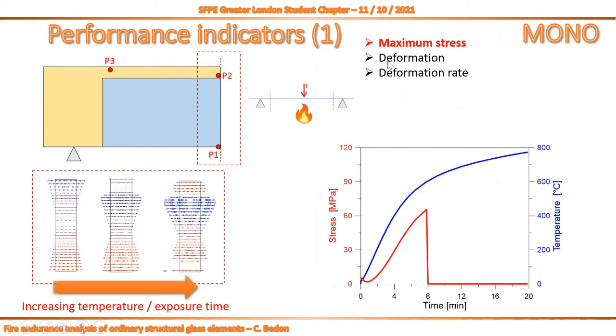So what happens if we take into account the three performance indicators, and we start from maximum stress. For sure, it happens that we cannot expect anymore that tensile stress peaks are representative of the bending behavior at the bottom edge of mid-span section. This is something that we can do in cold conditions only. But for sure, if you look at the other control points, P2 and P3, you will see that our tensile resistance is first exceeded compared to P1, just because of the modification of Young modulus and so modification of bending stiffness.